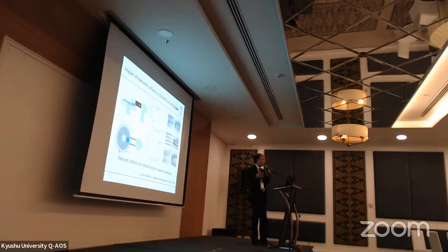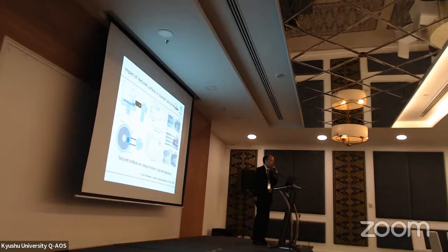This slide shows something different from hydrogen environment. It's just a normal friction lubrication test. This slide shows the impact of textured surfaces in starved lubrication. It's quite basic research. Recently, the viscosity of base lubricant oil has been required to decrease because friction in hydrodynamic lubrication should be decreased as much as possible. As a result of starvation, oil shortage tends to occur. But by using surface texturing such as a pattern, it's quite useful to recover oil shortage in contact area. You can see that the friction can be decreased by about half by using textured patterns on surfaces.